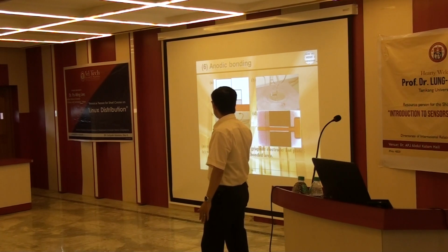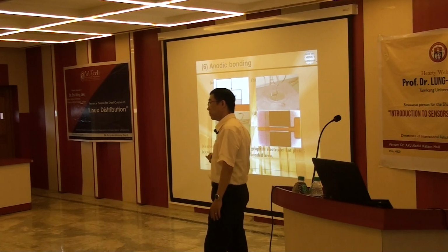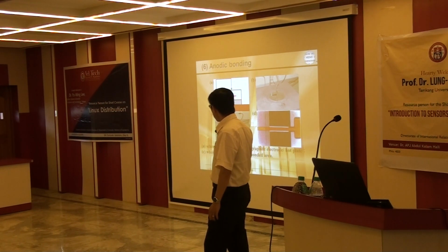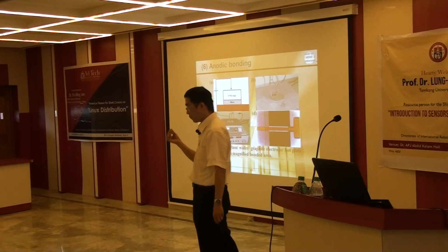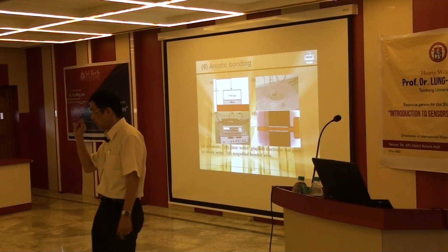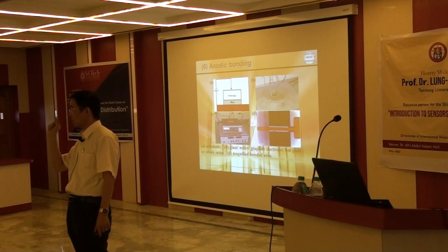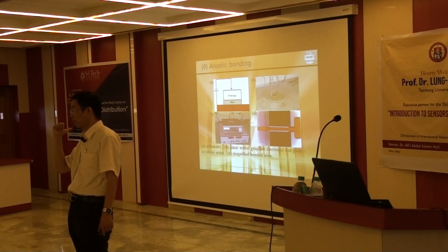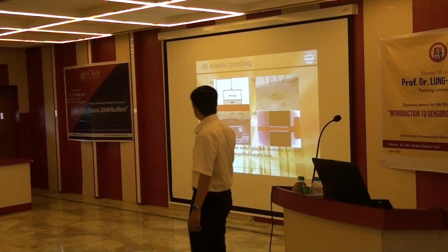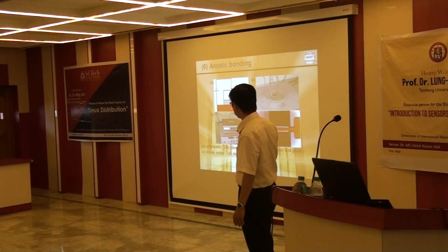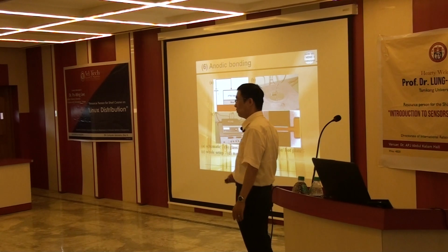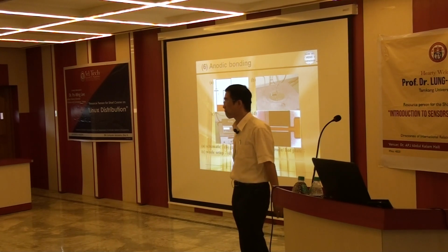Heating to a temperature of about 400 degrees C or 500 degrees C can induce some sodium ion transport. So finally, at the interface, some partial anodic bonding will happen. So these two conditions provide high temperature, 400 to 500 degrees C, and high voltage, 800 volts to 1000 volts.